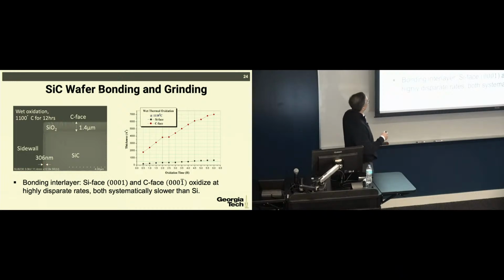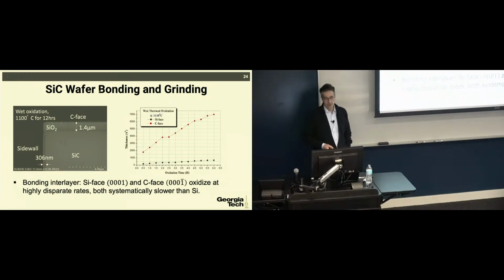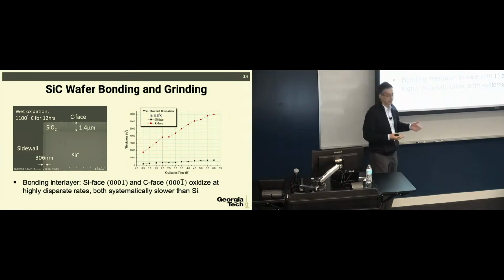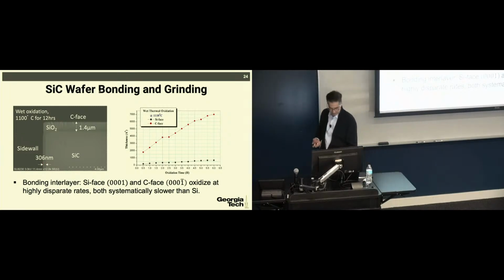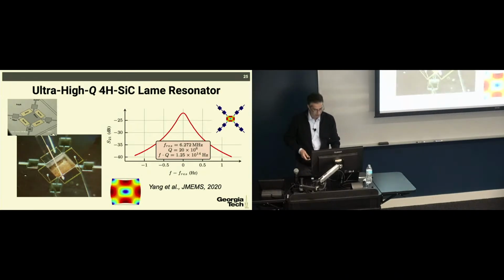So this is a very nice example of a trench etched into the silicon carbide. You see that the surface is carbon face and the oxide is 1.4 micron on the surface, while the sidewall is only 300 nanometer, okay? So bonding has its own intricacies, as well as the grinding and polishing, which requires an additional type of grinding tools and slurries and pads that are suitable for silicon carbide. So you go through all this hassle to process this device for what?